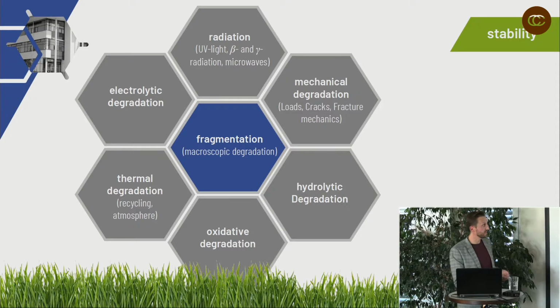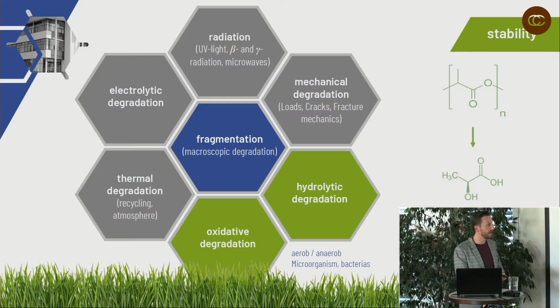Yeah, next to the physical degradation, we have thermal degradation, especially when we recycle it. That means the material has to melt down again. Yeah, and so there are problems with thermal degradation, and we have oxidative stress and hydrolytic stress. But if we have all of them, then it can be an advantage, because then with the help of organisms and also with the right atmosphere, with oxygen as concentration, we can have biodegradation. So that means we destroy the bonds, especially on our heteroatoms, like here the oxygen. Yeah, we degrade it to its monomers again, and they are fully degraded to CO2, to water, and if you have some other minerals or things like that, also to biomass.